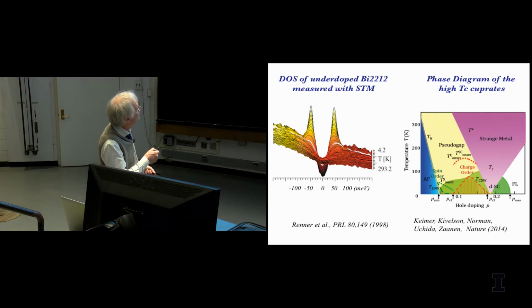Here we have a sample where in 1998 Renner and Fischer measured the tunneling spectra, which is actually density of states as a function of energy. And what you see is below Tc, there's a nice gap. Not a full gap, it's a D-wave gap. That's why it's not completely going to zero, a nice gap. You warm up, you reach Tc, that's where the white line is, and there's still a gap. You don't have these quasi-particle peaks anymore, but there's still a gap. And you go up to very high temperatures, even at 290 Kelvin in this particular case of an underdoped sample, there's still a little bit of a suppression around EF. So there's always a bit of a gap.